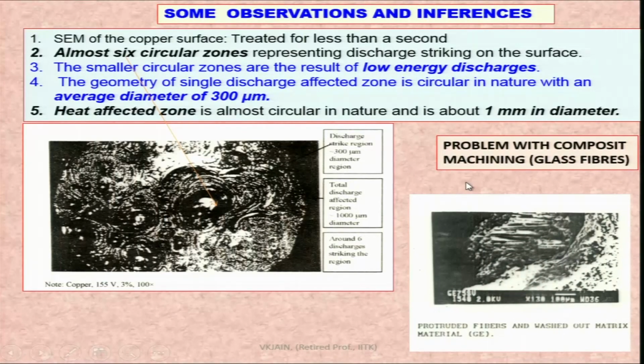And this is the problem with composite machining. We can see here composite materials have two constituents, one is the fiber, another is the base material, and both may have different thermal properties. So, the one which has the lower melting and vaporization temperature will get melted out, as you can see over here, and glass fibers, having a higher melting temperature, remain there. So, it does not give you a very accurate machined surface, and that is why one has to first analyze the process, and before really using it for practical purposes, one has to be careful.